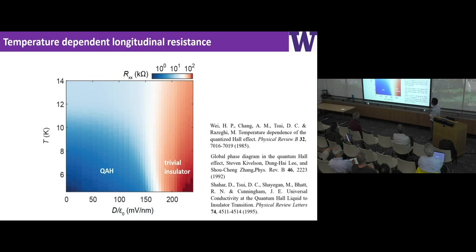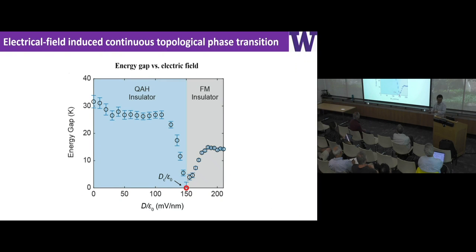I'm going to skip all these, actually, for the interest of time. This next part I want to show you. What I mean here is that we measure the thermal activation gap of this quantum anomalous Hall insulator as a function of the electric field. So we see that this thermal activation gap is about 30 kelvins. As we tune this electric field, the gap eventually shrinks and vanishes, then increases again when it transitions to a ferromagnetic insulator that is topologically trivial.